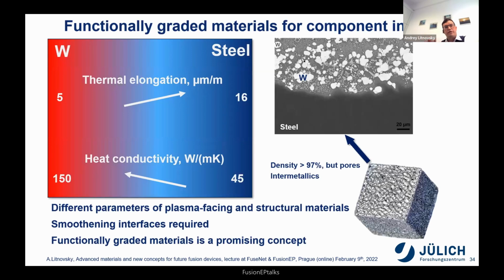The plasma-facing material needs to be joined to the constructive material, the structural steel, and we see a number of parameters which are very different between tungsten and steel. Thermal elongation is 3 times less for tungsten, heat conductivity is 3 times more for tungsten. It's like a magic number, 3 times, but every time in different directions. So the idea is, as you've seen, you're adding the powder, but you can also change the powder. You can mix the powder and make so-called functionally graded materials, gradually going from tungsten to steel, or from steel to tungsten.